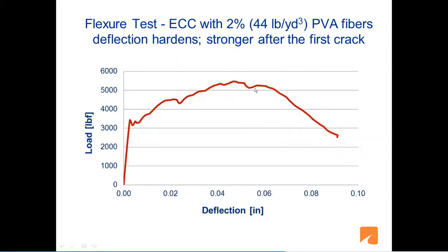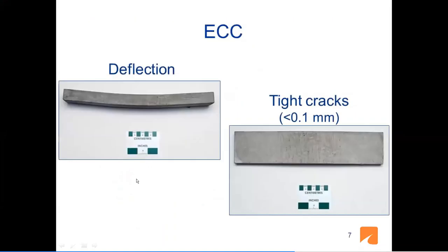So this phenomenon is known as deflection hardening. It is stronger after the first crack. So since it's strong at that location when it has a crack, it doesn't get wider. Another crack forms next to it. So you end up with multiple cracks in this concrete. As we discussed, this is the load versus deflection curve and how it got stronger.